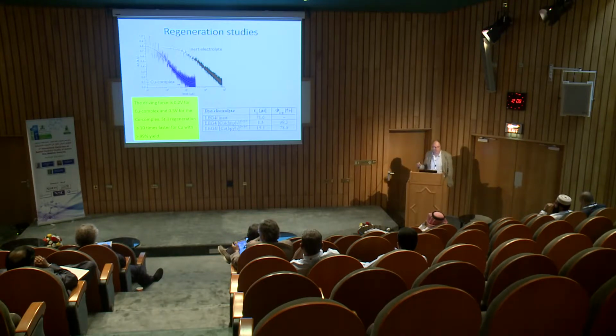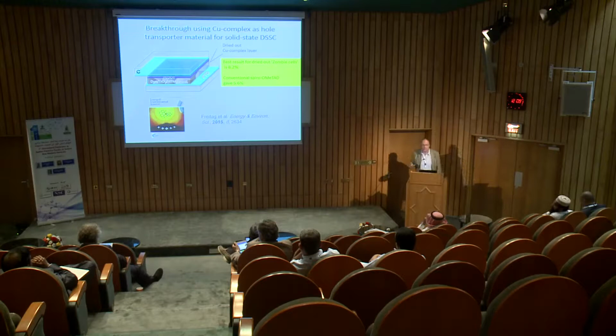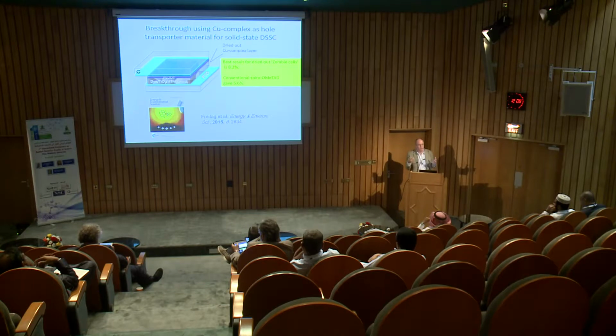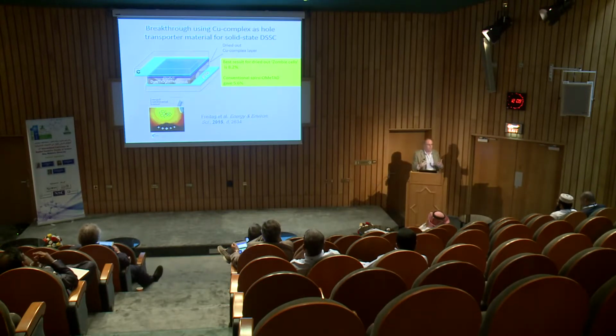So this is where we are at the moment. We are now trying different dye molecules to see if we can benefit from this very efficient dye regeneration. We had another surprise just to finish the dye sensitized talk, and that is that normally when we work with this liquid electrolyte in a dye cell, of course one can imagine that there is a problem with leakage of the electrolyte. It's a liquid, and if the sealing technology is not good enough, we can have evaporation problems of the solvent. And what normally happens if we have a cell which has dried out, we have a leakage problem, and it's dried basically, is that they are dead.